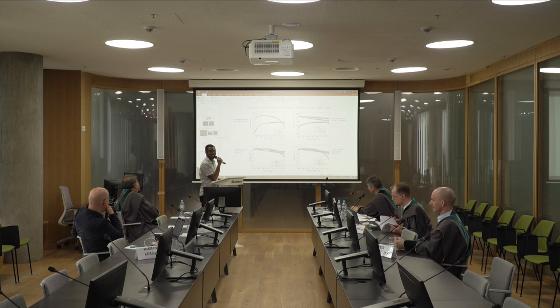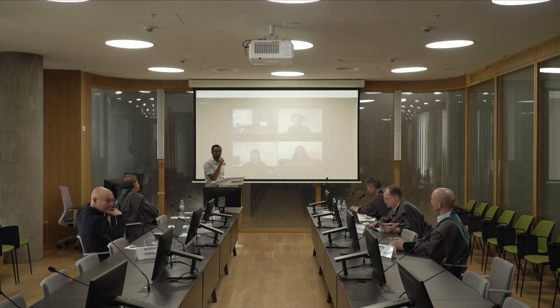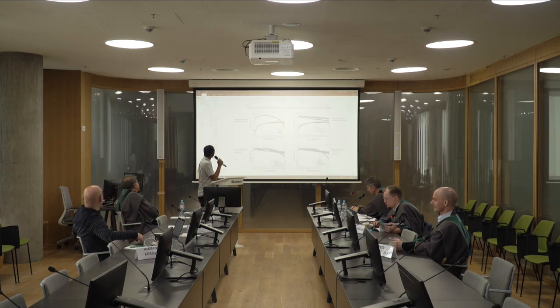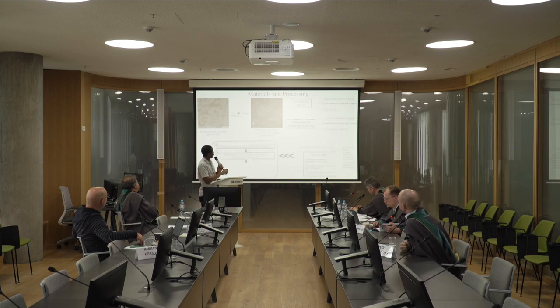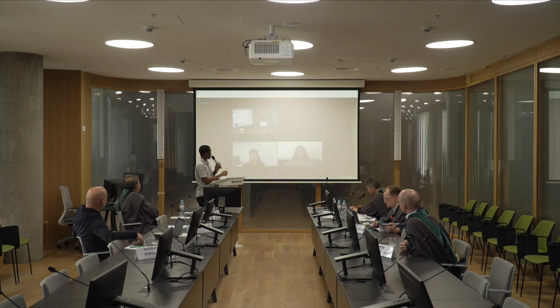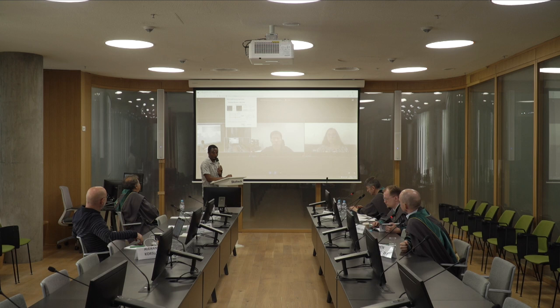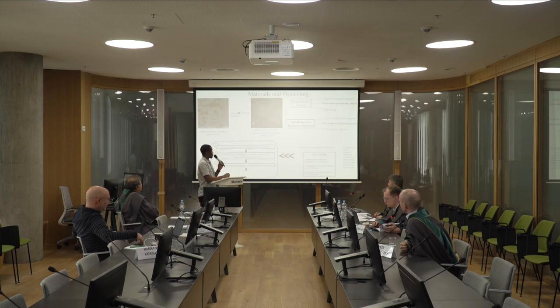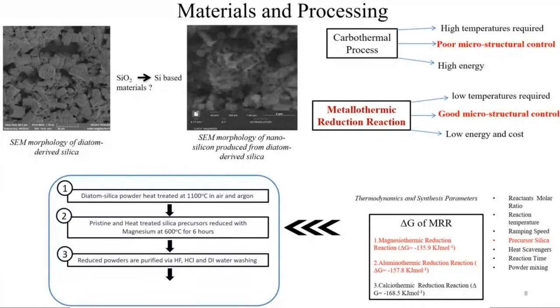It should be slide 8. Thank you. Yeah, so a better nanoscale morphology is one that has some features from the precursor diatomite powder. As we can see here, this is the same morphology of the nanosilicon powder we obtained. It has some nanoporous details from the precursor powder. So that's what we mean by better nanoscale morphology. Because if we obtain silicon but destroy the nanoscale morphology from the precursor, then we might as well use other means to just produce silicon.